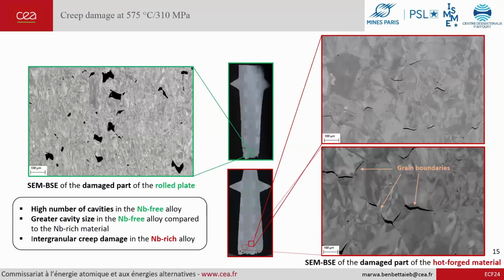If we move on to observe longitudinal sections of the two alloys, at the same area from the damaged part of the two specimens, we can see on the left that we have a higher number of cavities with greater cavity size for the niobium-free alloy. And we can note that the fracture is intergranular for the niobium-rich alloy, because the cavities follow the grain boundaries. But we can't conclude about the type of fracture of the other alloy.